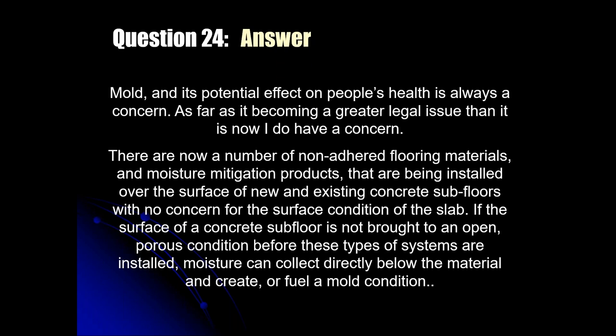My experience with those type of systems, as well as some of the non-adhered sheet moisture mitigation systems: if you don't open up the surface of that slab, particularly if you're a slab on ground without a vapor retarder, so that the rising moisture that condenses underneath these PVC rubber-backed carpet tiles or sheet vapor retarder membranes can be reabsorbed into the surface, you end up with a film, if you will, of liquid water underneath the flooring and underneath the systems.